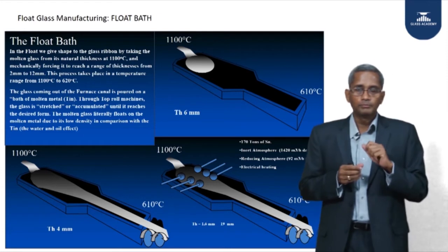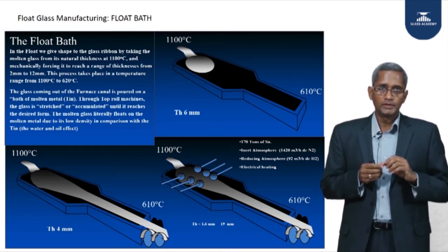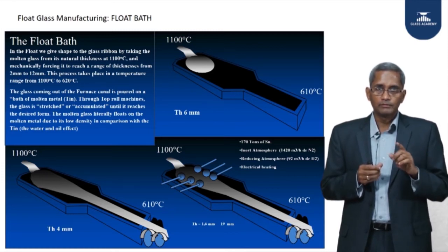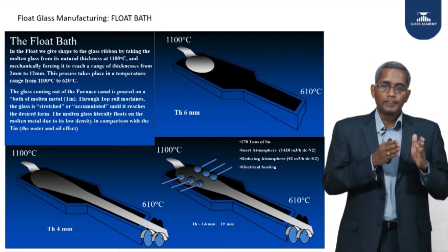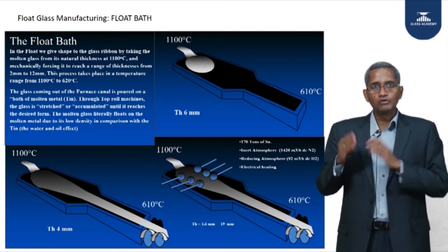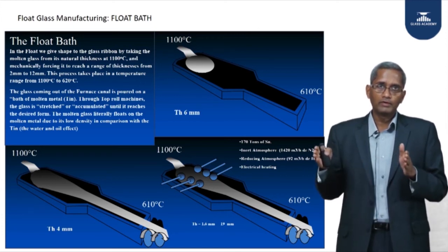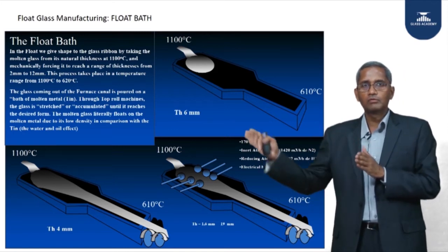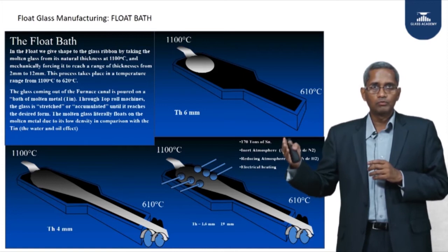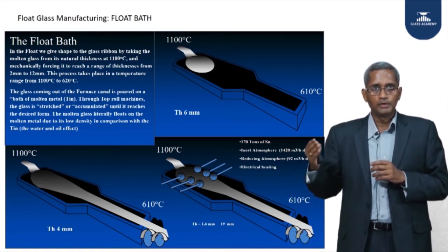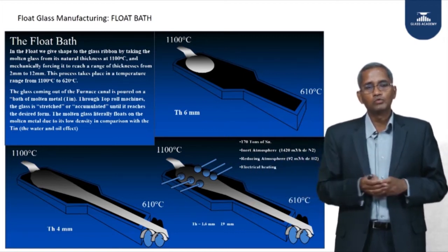For example, if the first top roll pushes glass at 2 meters per minute and the second top roll is set to 3 meters per minute, the same quantity of glass now travels faster, covers a larger area, and the thickness reduces. Increasing the third top roll to 5 meters per minute reduces thickness further. So for very thin glass like 2mm or 1.6mm, we employ more top rolls and incrementally increase speed to progressively stretch the glass thinner.